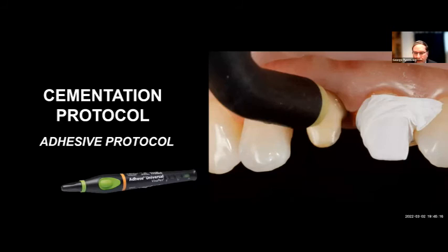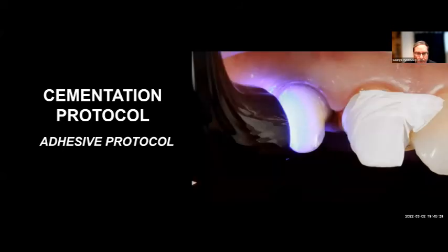And then we air dry it and basically light cure it accordingly. We're working now on some of the dual cure versions, but basically by air drying it and bonding it in place, we create a very strong pre-sealed bond of the restoration. Here we're curing it, 10 seconds. And then we proceed with basically loading the restoration and seating it accordingly.